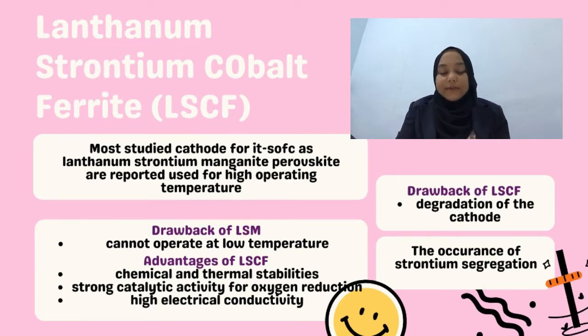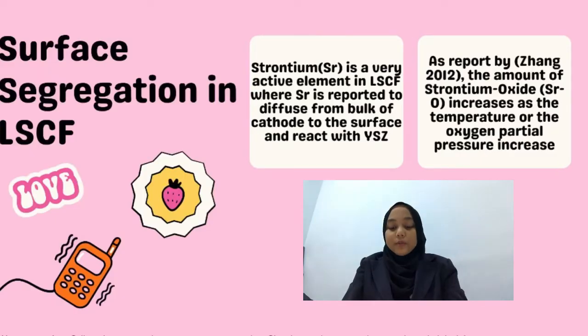Another drawback of LSCF is the degradation of the cathode that is caused by the phase decomposition of LSCF within a 15 nanometer thick surface region. The degradation also occurs due to the Si contaminants that are accumulated in the cathode of the SOFC stack over time, and the strontium segregation that occurs on the cathode surface and the interface of electrode and electrolyte. As mentioned before, due to the Si contaminants that are accumulated in the cathode of SOFC stacks over time, surface segregation occurs in LSCF. Sr surface segregation, which is known as strontium surface segregation in LSCF, has been reported by a few groups.